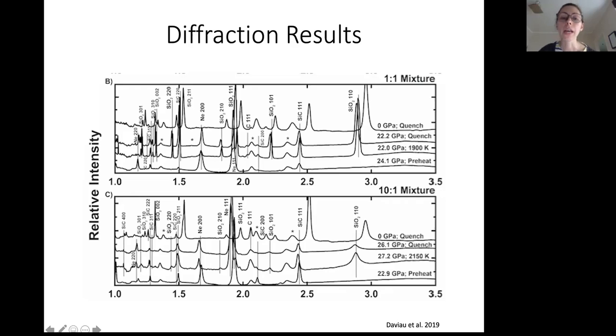We heat this up to 2000, 2500 Kelvin in some cases, quench the sample, and then see, do we observe any reactions? We don't really see that much happening. We still see silica, we still see silicon carbide. The new phase we observe is again that carbon diamond, indicating that the silicon carbide is still breaking up, there's still carbon coming out. These results are pretty much identical for the 10 to 1 mixture. I don't have it shown here, but it's also very similar for the 50 to 1 and the layered mixture. So we don't really see any oxidation reactions happening with these compositions at these pressures and temperatures.